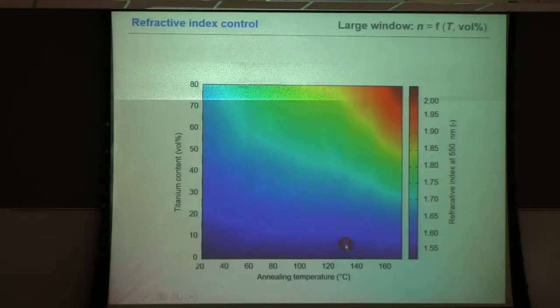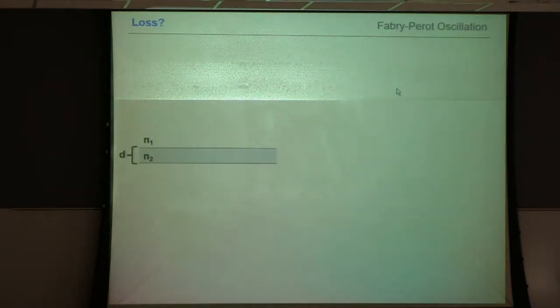So just to summarize, we have a simple material where, with titanium content and annealing temperature, we can change the refractive index from 1.55 for the neat material to around 2.1 when we go to very high titanium content. We can look at the loss, though, also. As I said, higher refractive index composites, hybrids, have been shown. But what is really critical in case you want to do photonics is that you do not have optical loss, meaning absorption, scattering, etc.